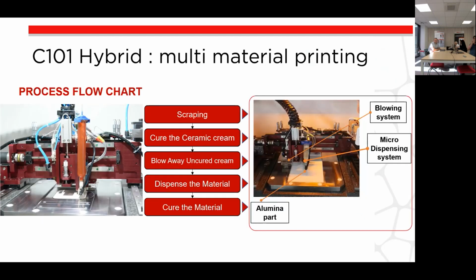Just a little bit of an insight on the C101 hybrid. So just to show you how it works on the machine, a little process flow chart. So it's the same principle as normal SLA. So we would scrape a layer, 25 microns to 100 microns, depending on the material that we are using. We will then cure the slurry with the laser, the same as the normal process. And then we will blow away the uncured slurry.